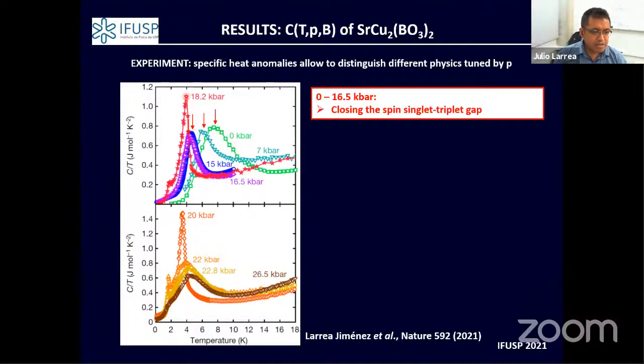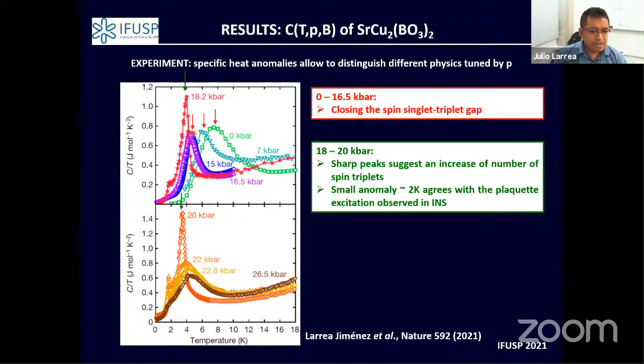When you apply pressure, this hump starts to decrease up to roughly 16.5 kilobar, but at 18 kilobar a sharp peak simply appears in the specific heat. This tells us that there is something very different from simply the decreasing of the spin gap related to the separation of the singlet and triplet state.